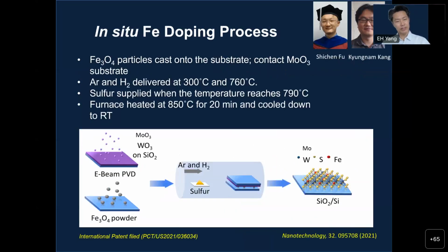Then we add iron oxide particles cast onto the substrate. Basically, we contact this with the molybdenum trioxide film deposited substrate. Then we supply carrier gases, argon and hydrogen, as well as the chalcogen vapor. That's from the sulfur powder, which you melt and then vaporize. So you have to find the right time or the right temperature, the right moment, before the furnace is heated at the high temperature for the growth and cooling down.